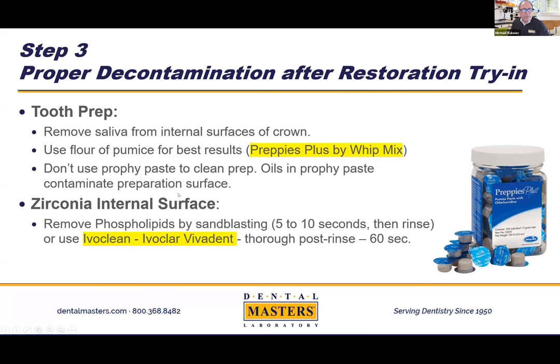Step number three, we want to properly decontaminate the restoration after try-in. That means that we want to remove saliva from the internal surfaces of the crown. We recommend the use of flour pumice for best results. Preppies Plus by Whip Mix is a good option. Do not use prophy paste to clean up the prep. The emollients, the oils in the prophy paste will act to contaminate the preparation surface on the internal, and this has been an area that has led, early on, I think, maybe not so much today, to a lot of debonding of restorations, particularly when used with resin cements.